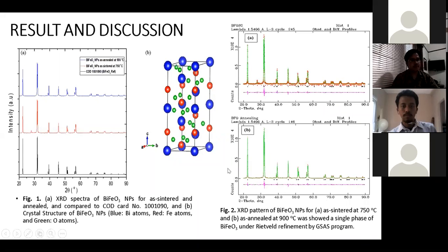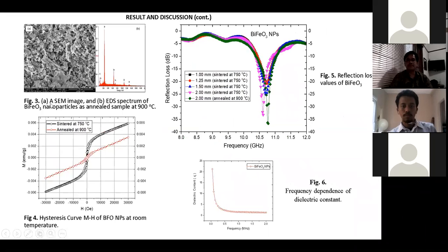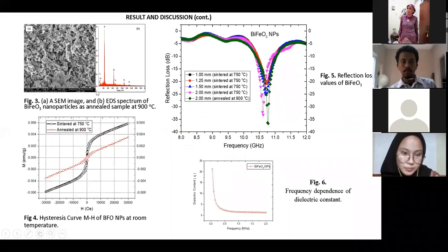Figures 3a and 3b present the typical scanning electron microscope image and energy dispersive spectroscopy spectrum, respectively, after annealing at 900 degrees Celsius. The average crystalline size of BFO is about 71 nanometers to 135 nanometers. The room temperature magnetic hysteresis loops up to a magnetic field of 30 kilo-oersted were measured for the BFO samples sintered at 750 degrees Celsius and annealed at 900 degrees Celsius, respectively, as shown in Fig 4.